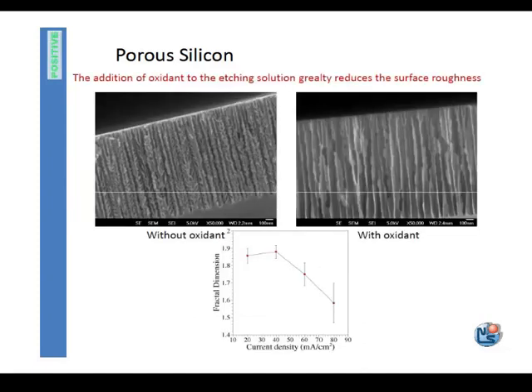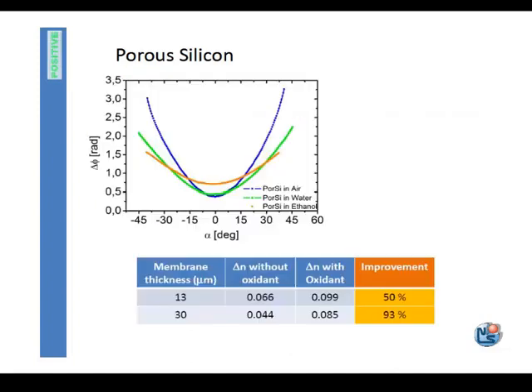Then we improved the etching method, and from such a highly branched structure, by modifying the etchant composition, adding some oxidant, we are able to greatly reduce the roughness, and the pore becomes a much straighter pore with a smoother surface. We performed a fractal dimension analysis, and we checked that the fractal dimension decreases because the etching reduces the surface roughness within the pore.